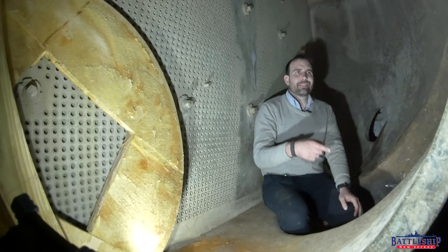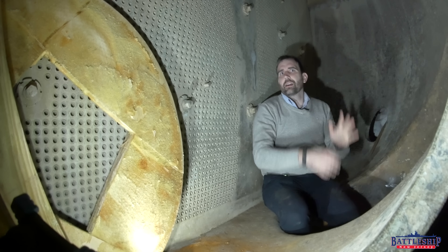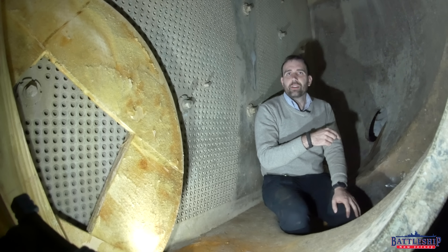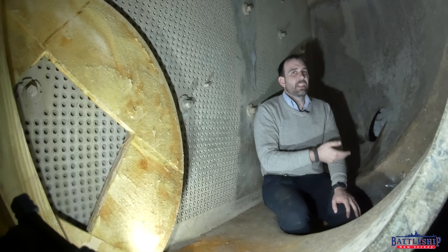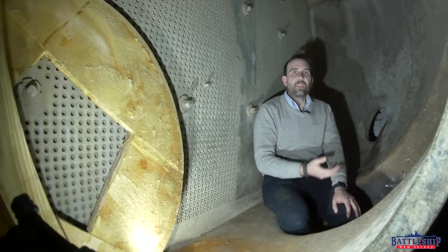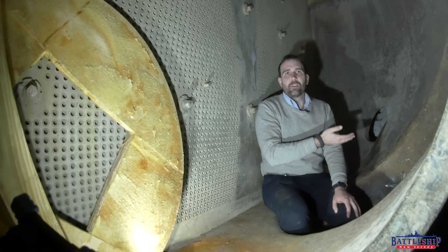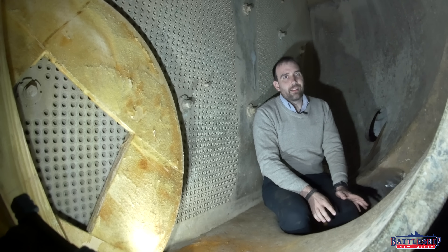Some of those blanks sort of look like bowls where they're welded onto the side; some of them are flat doubler plates welded over. This particular one failed — the exterior plate rotted away. It was almost certainly thinner than the rest of the shell plating and is metallurgically different from the rest of the hull, causing bimetallic corrosion. And the weld bead is different from both the metal of the plate and the metal of the ship, so you get trimetallic corrosion.